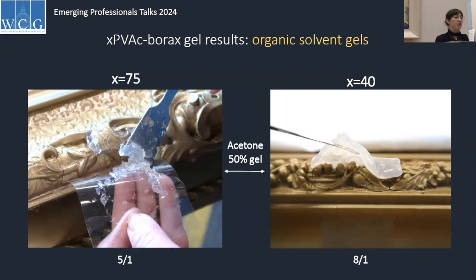And this is interesting because the literature does say that the 75 PVAC and the 40 PVAC are both good for organogels. And they do gel and they are workable, but they do greatly differ in their degree of elasticity and moldability and cohesion in that complex. And so the 40 PVAC gels were very good to work with.